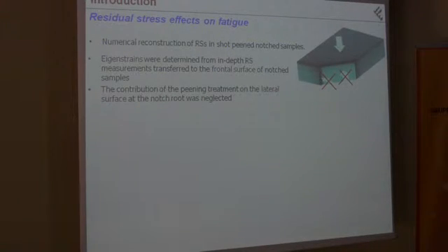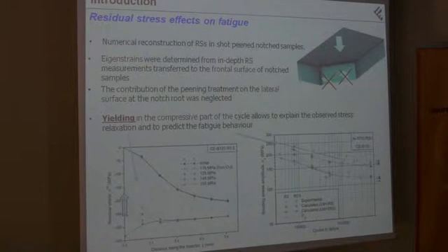To model the residual stress, which was measured by XRD analysis, we introduced the residual stress in a finite element model, considering only the frontal surface of the specimen. The reproduction of the fatigue results is quite good, and we can also observe the stress relaxation as a function of the applied stress.